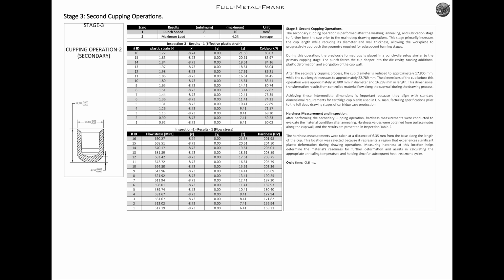Hardness measurement and inspection. After performing the secondary cupping operation, hardness measurements were conducted to evaluate the material condition after annealing. Hardness values were obtained from surface nodes along the cup wall, and the results are presented in Inspection Table 2. The hardness measurements were taken at a distance of 6.35 millimeters from the base along the length of the cup. This location was selected because it represents a region that experiences significant plastic deformation during drawing operations.